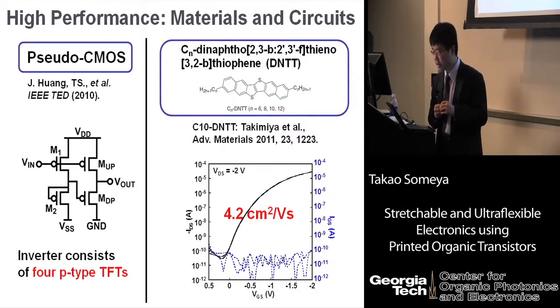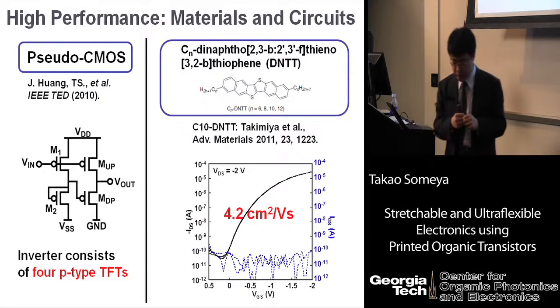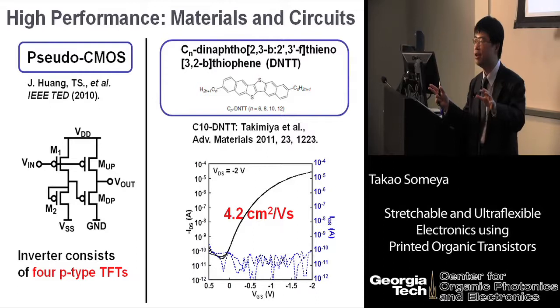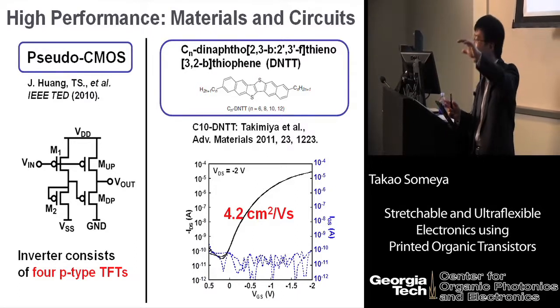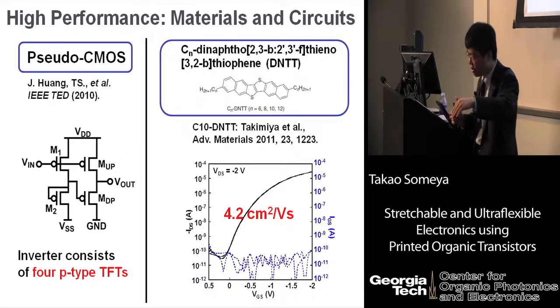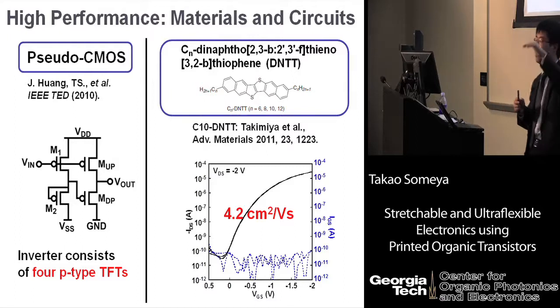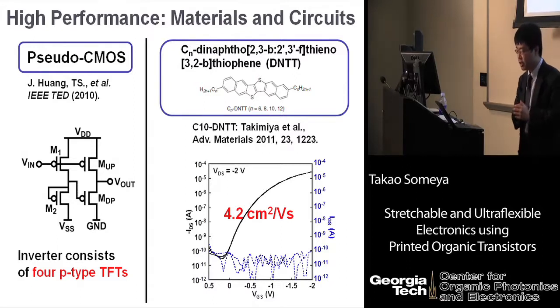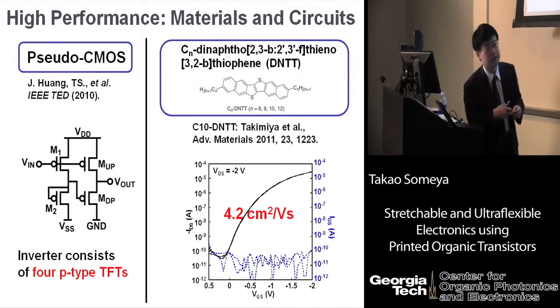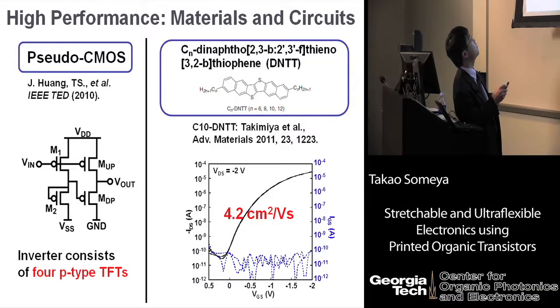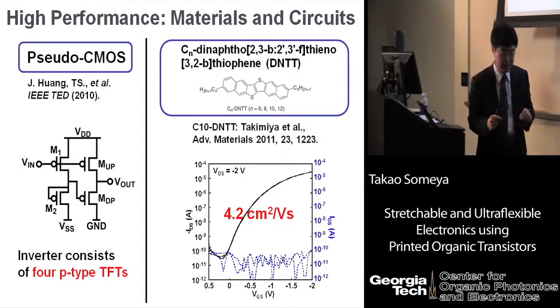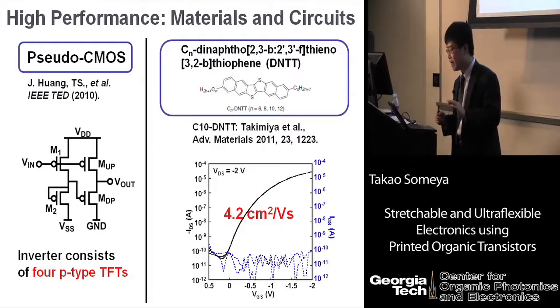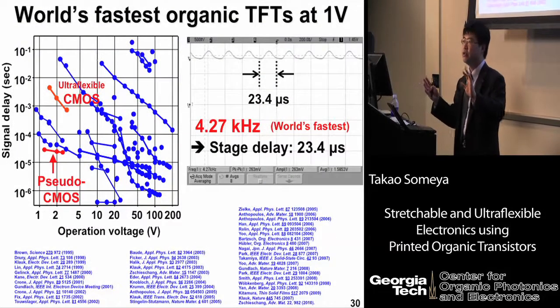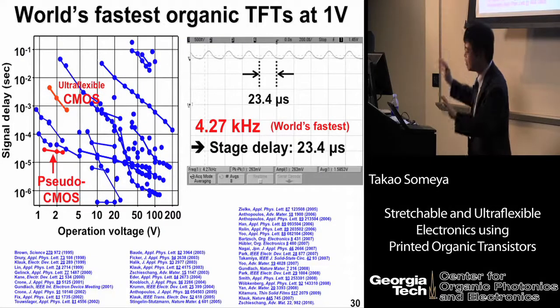Another approach that I adopted is to use the novel pseudo-CMOS layout. Of course, CMOS requires both P-type and N-type semiconductors. However, N-type semiconductors still have an air stability problem, degrading quite rapidly in air. And also, the mobility of N-type semiconductors is usually much less than that of P-type semiconductors. That ultimately limits the electronic performance of CMOS. To remove the bad aspects of N-type semiconductors, here we use the pseudo-CMOS circuit, which comprises only P-type semiconductors.